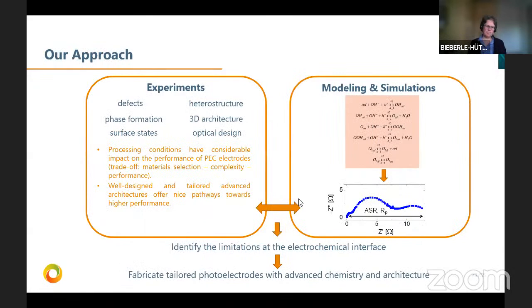So I've shown you now from the experimental side how defects, phase formation, surface states, 3D architecture, how we can study these and get a lot already out of them in order to make better electrodes. So the processing conditions have considerable impact on the performance, and it's really a trade-off between the material selection, the complexity of the structure, and the performance. And we also have seen that well-designed and tailored advanced architectures offer a nice pathway towards higher performance. And I bring this in the light a bit of this discussion: should we go to more complex metal oxide structures, or should we better stay with simple oxides? So this is seen a bit in this entire discussion.